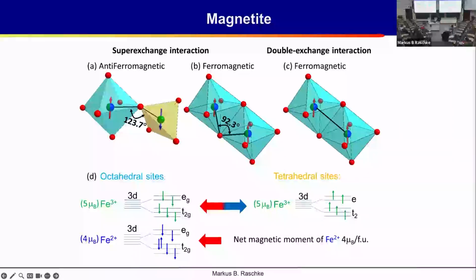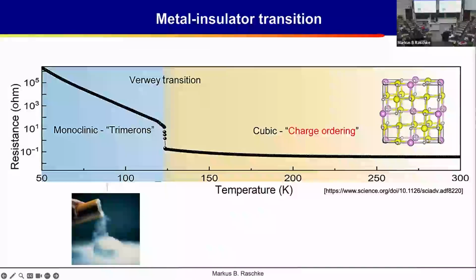So then there was an interesting experiment done, which is in some ways surprisingly late. And if I had had more time this morning, I could have demonstrated this to you. We could use a voltmeter and apply a voltage across this crystal, and we measure a current. And we would see that magnetite is a conductor, not the best, not as good as iron, because of these oxygen atoms through which the electrons have to hop, but it is conductive. And in 1940, a Dutch physicist cooled this crystal and recognized that there is a phase transition. And this conducting behavior changes as you start to cool.